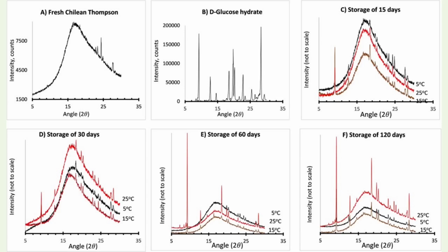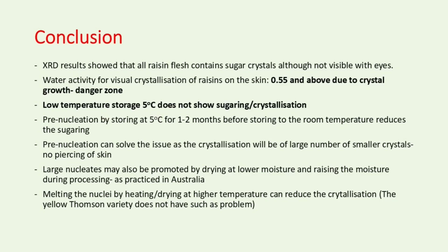In parallel, it was done in Chile as well, at a university, similar sort of work. So finally, our analysis was that the XRD results showed that all raisins contain trace sugar crystals, although not visible to the eyes. All of them have sugar crystals, small sugar crystals, but not visible to the eyes. Water activity for visual crystallization is the danger zone. I told you, if the water activity goes above 0.55, there is surface crystallization.